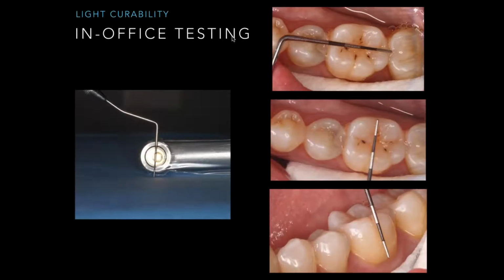Here's another test that you can take. Take your periodontal probe and measure the depth and the width of your curing light. If the average clinical crown height of a posterior tooth is 6 to 8 millimeters, clinicians may be faced with a little bit of challenge today to make sure that that light can adequately cure into a deep preparation, because there's definitely a significant difference from the curing light tip to the base of that proximal box. Given that the average class 2 depth is 6 millimeters, and then, like I was talking about earlier, you add on a cuspal deflection, maybe a matrix or a ring system, that height can easily jump up to 8 millimeters. So without a complete cure, again, the restoration is going to fail, with secondary caries and, of course, post-operative sensitivity. And we certainly don't want to have patients having that.